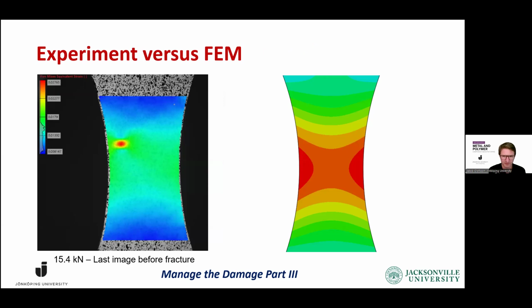So comparing the strain fields that we see to the left with what we would expect to see to the right, we can see that it's definitely not behaving the same way as we would expect. So this hidden damage has really caused the deformation and the fracture of the material to behave differently than it would if this were just a continuous material, and we would just have dislocations moving, etc. The deformation behavior has really changed by this hidden damage.